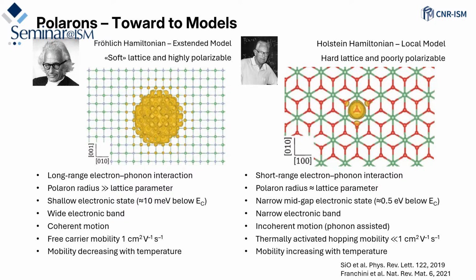Considering the Holstein polaron, so the small polaron, we have short-range electron-phonon interaction. The polaron is just localized within the unit cell, as I mentioned. We have narrow mid-gap electronic states, which can be half an electron volt, so very narrow and very deep. And in this case, the motion is incoherent, so it's phonon assisted. This means that the mobility is increasing with the temperature.